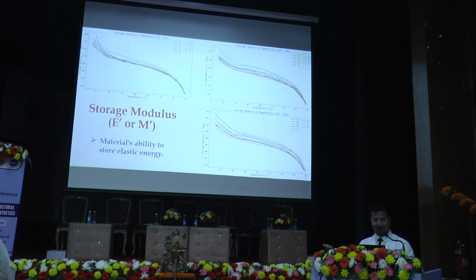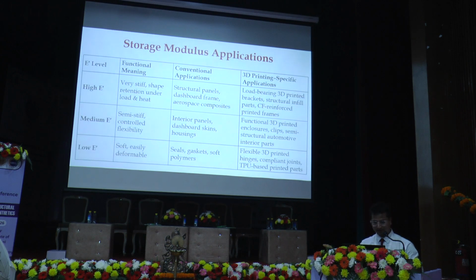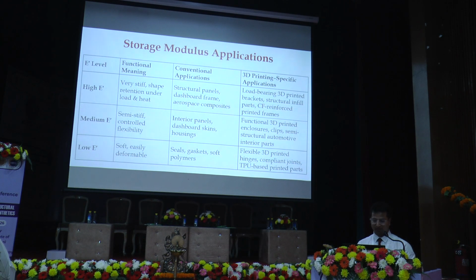So these are the combinations. I wanted to see in which curve the storage modulus is high. If storage modulus is high, then that material is more stiff. In this, you can see in the pink one, we got the high storage modulus. I would not always want my storage modulus to be high. It depends on the application. If you have high storage modulus, then the applications are different. If you have medium storage modulus, then the applications are different. And similarly for low storage modulus, the applications are different.